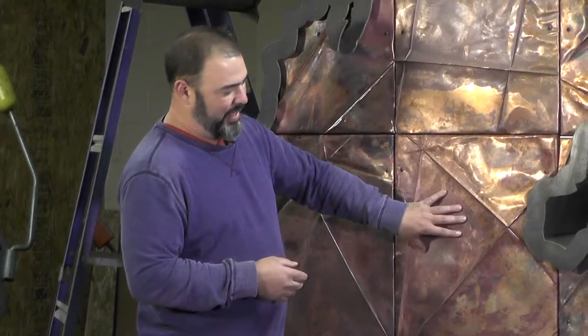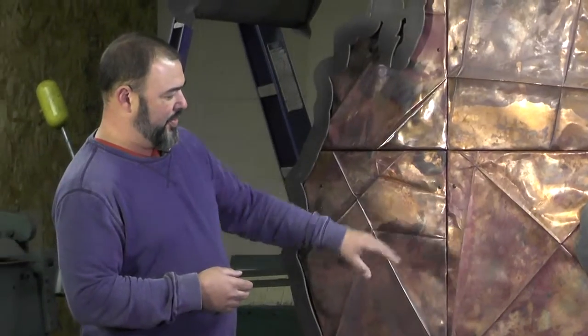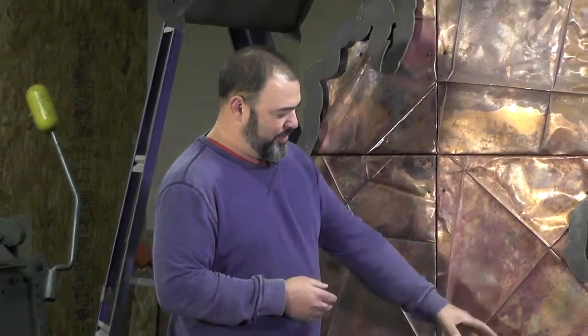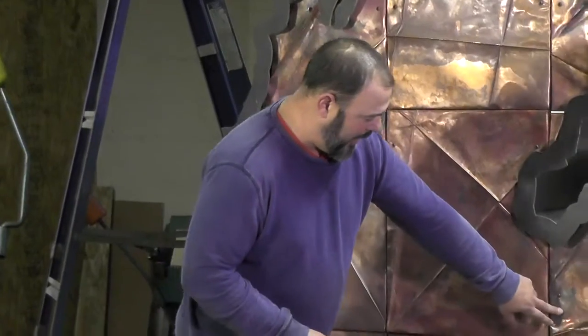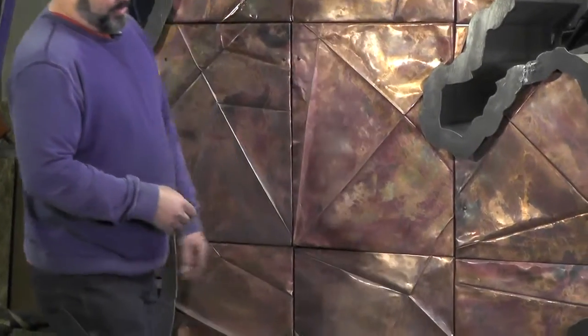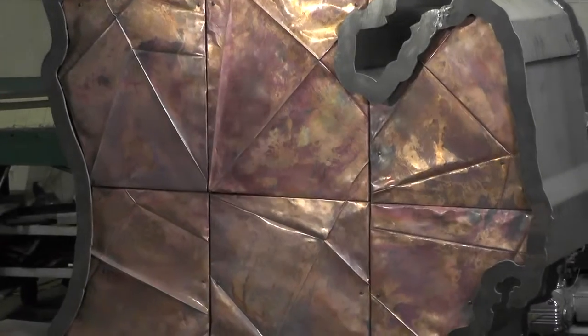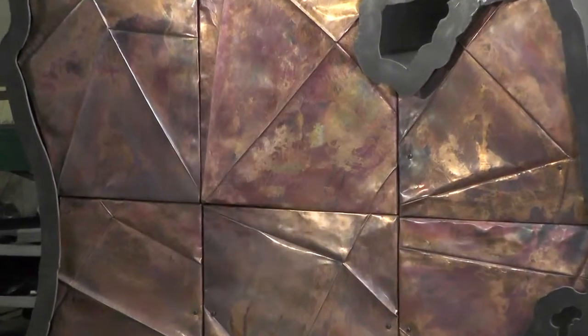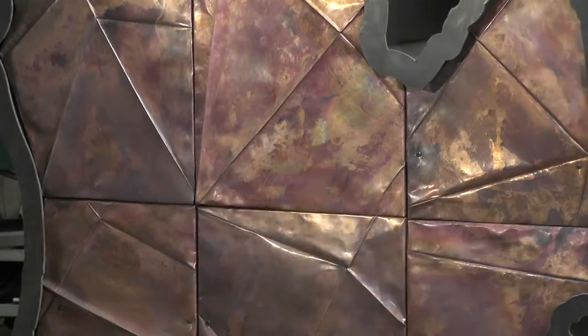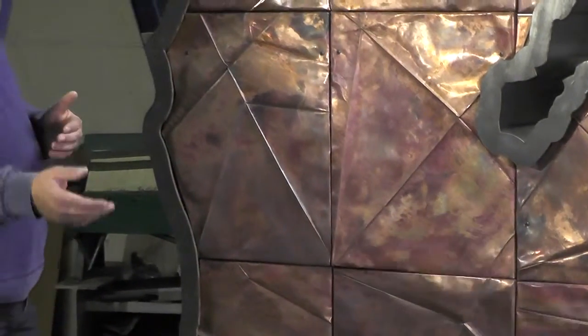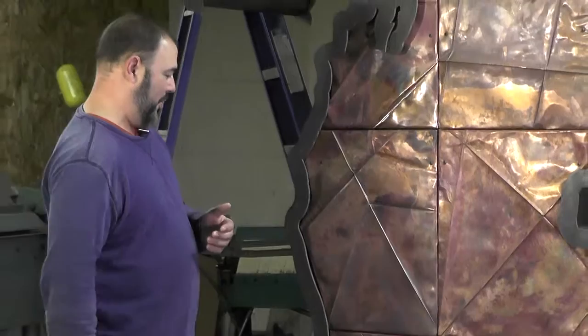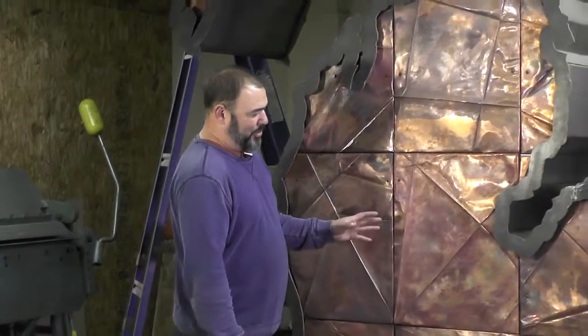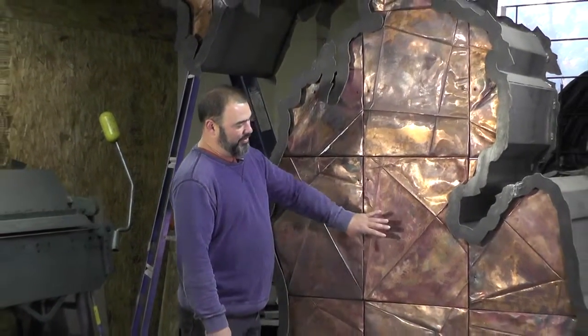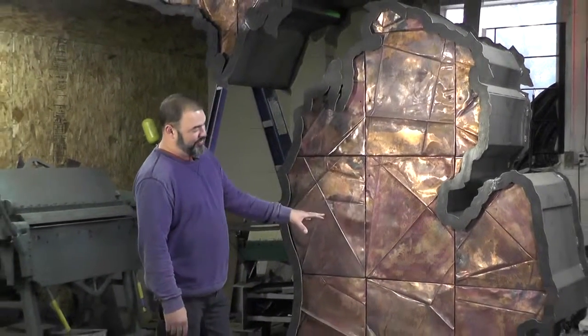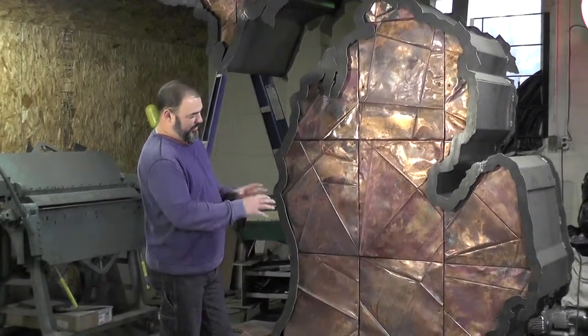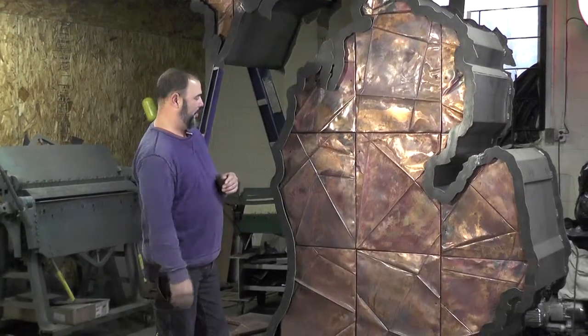Evidence from heating is locked into the surface in the form of patina, and that's these reds, and you get some green tones, blacks, and various brown tones. All of that comes out after a series of annealing, quenching, folding, re-annealing, quenching, unfolding, and so on and so forth. Each of these panels is probably folded, annealed, unfolded and refolded five or six different times to get this series of bends and the coloration that we're looking for.